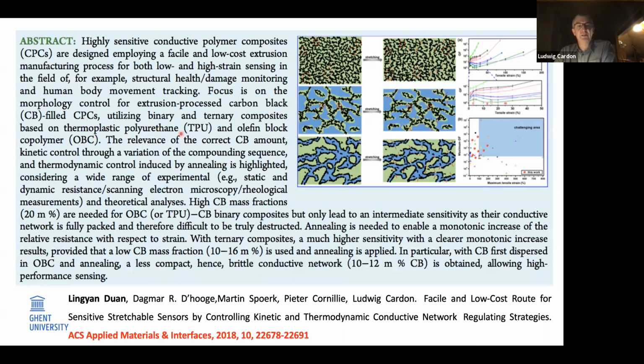We combined, in this case, standard TPU with OBC. By blending them in the right blending percentage, we also involved the so-called carbon black fillers, and in the most ideal situation you see here on the bottom, we created a kind of sensitive network. In this sensitive network, depending on the stretching behavior, we could achieve the gauge factor and strain behavior, the red dots you see on the slide. We could develop sensors with high sensitivity combined with gauge factor and strain possibility.